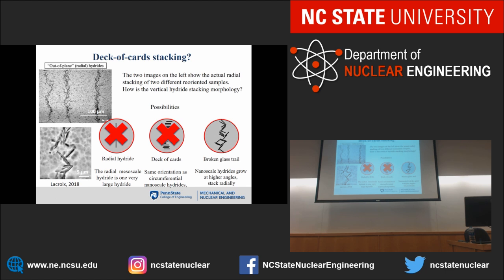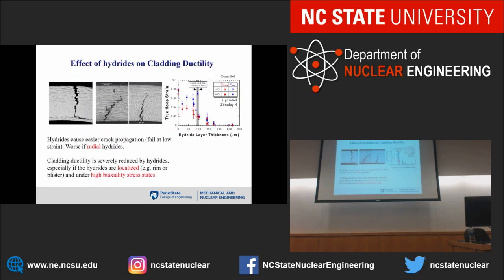To look at this, this is 5 microns here, you can see. A very detailed etching procedure showed this much like that. This is what they call a broken glass trail. What causes this? I can come up with an explanation maybe why it goes like this instead of going like that, but why do they stack up? Right? So there's some sympathetic precipitation going on. The presence of one hydride implies the precipitation of another, and this is kind of what we're investigating.